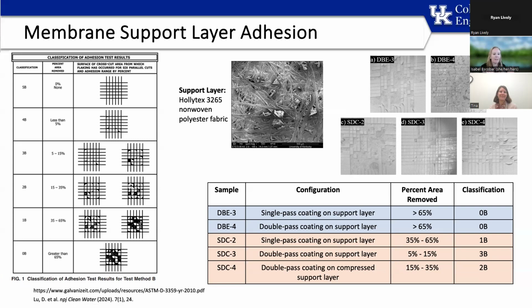And ASTM has a method where a grid is made on the membrane. You can see that here on the membrane, and this is what the grid looks like. And then it provides the details on how to attempt to scratch and pull it out. And then on observations, if none of it comes out, it is considered to be a 5B. If all of it comes out and there's absolutely zero sticking to the porous support, it's a 0B. And then there is everything else in between. And the first thing to notice is that the slot die made a better attachment. Now, in some of the cases, especially here with the doctor blade, we were right there.